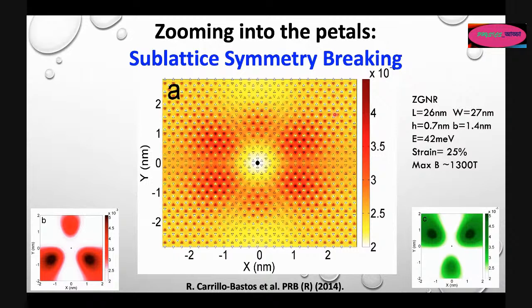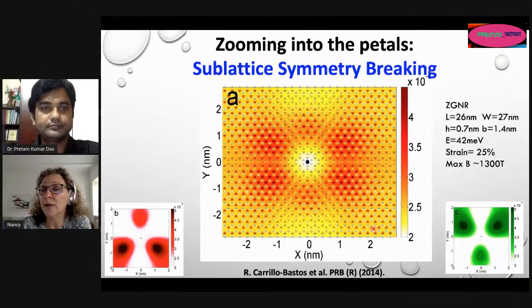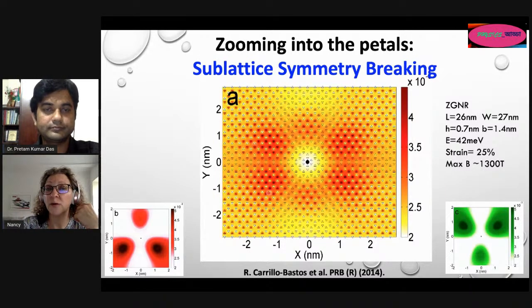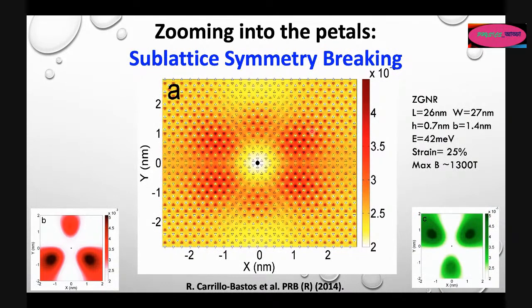Now, if I move to another region of the sample and I go here, I have another hexagon where the triangles that are dark now are the ones pointing up. So what this is saying is that the charge is accumulated in these regions. Clearly, I have the 6 petals here, as I saw before, but in each petal, the charge is unevenly distributed between the 2 sublattices, with one sublattice being much more occupied, hosting more electrons than the other sublattice. And this occupation alternates from petal to petal.